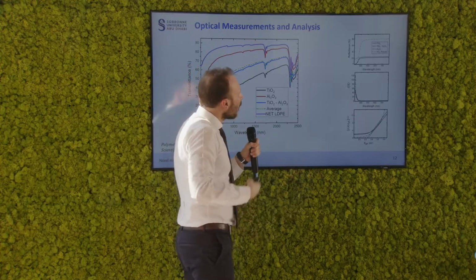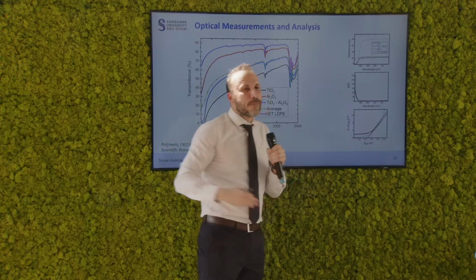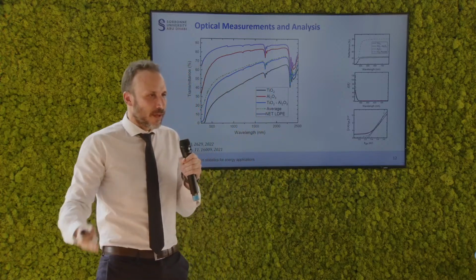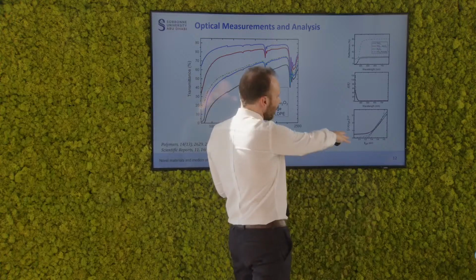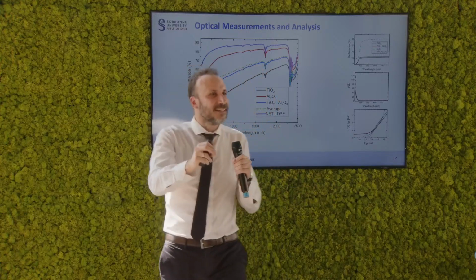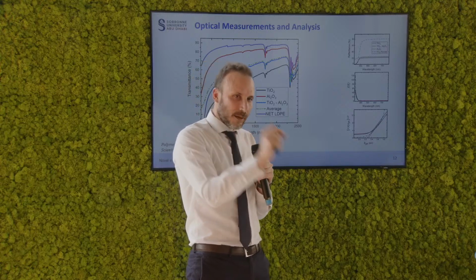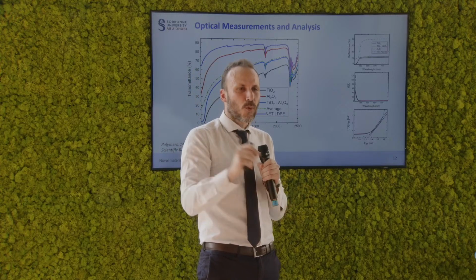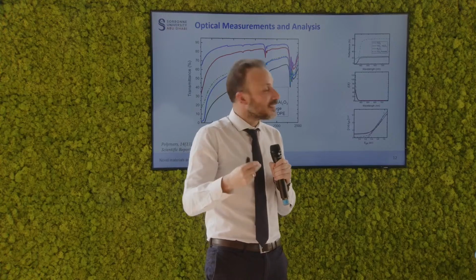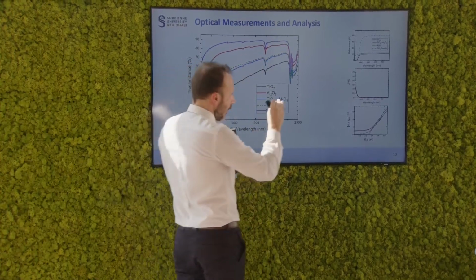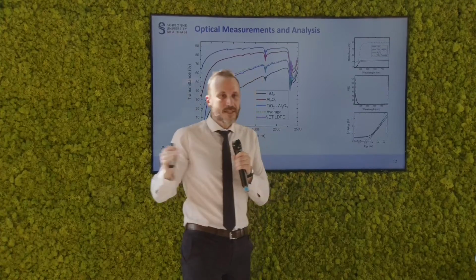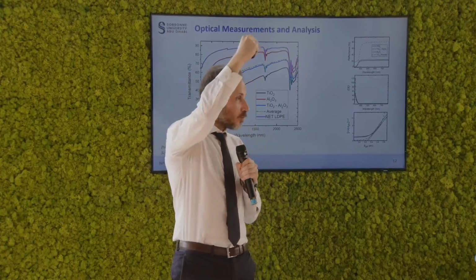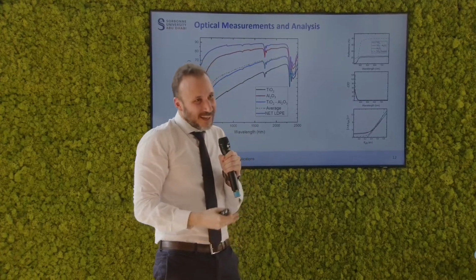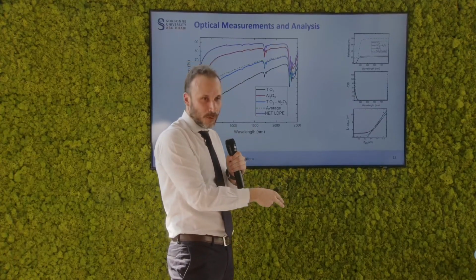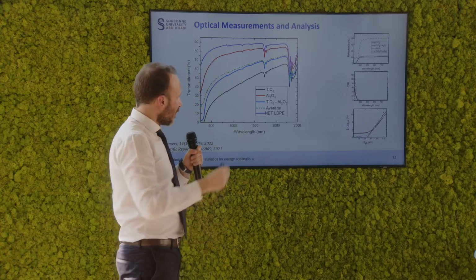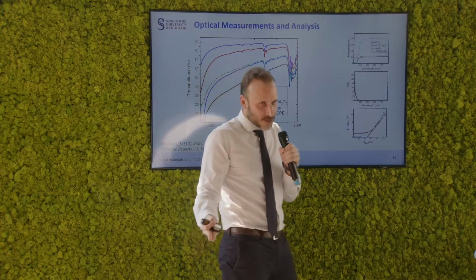By conducting some additional measurements of reflectance and applying some analysis which is based on the Tauc method, we're able to extract the energy band gap of these samples, which is fine. The idea is that we can connect that immediately to the particle size because of quantum confinement. So what we have established here is that the particles in the final product have the same size as the particles as they were received at the very beginning. This has been a kind of violent process that we have taken them through, and we would like to establish that indeed their sizes have not altered, at least the primary size of the particles.